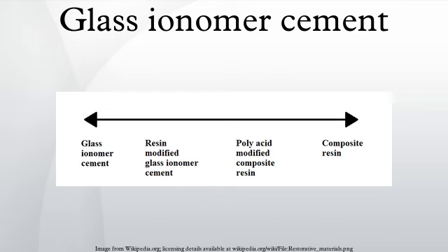As adhesive cavity liners, the so-called sandwich technique involves using GIC as dentine replacement and a composite to replace enamel. These purpose-designed lining materials set quickly and can be made receptive for the bonding of composite resins simply by washing the material surface if the material is freshly placed. This surface should be coated either with an unfilled resin or a DBA to optimize attachment.